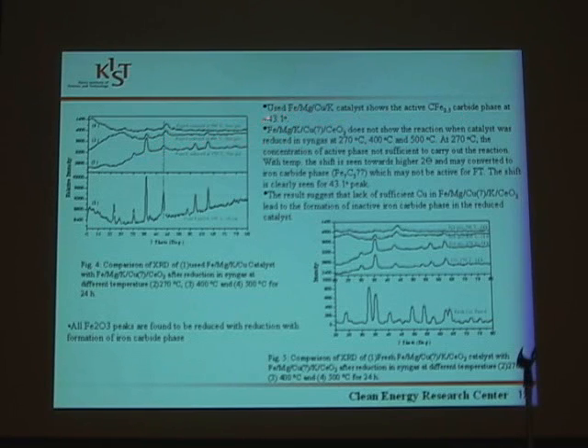This explains again that the Fe-Mg-copper catalyst shows the active carbon Fe carbide phase at 43.5 here. The magnesium promoted iron catalyst on ceria support does not show the reaction when the catalyst was reduced in syngas at 270, 400 and 500. And here, even if the active phase iron carbide was found, the concentration of the active phase was not enough to carry out the reaction. That is why it has not shown the reaction.